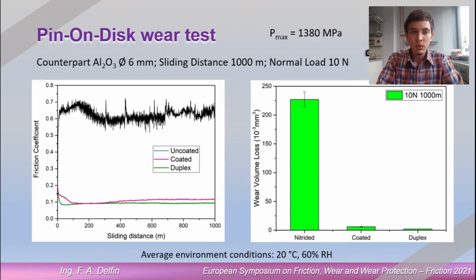So moving on to the wear test, we use the pin on disc first with 10 Newton load. This is for you to get an idea of the uncoated sample. 0.65 around is the friction coefficient with this load. And we see with the coating, the friction coefficient is around 0.1. It's really low, really good effect on there. The coated sample is slightly higher, but they are pretty much in the error range between both of them.